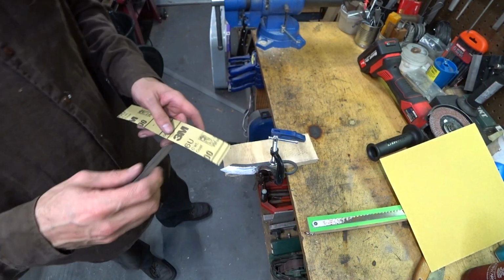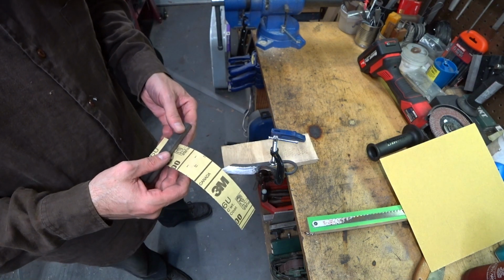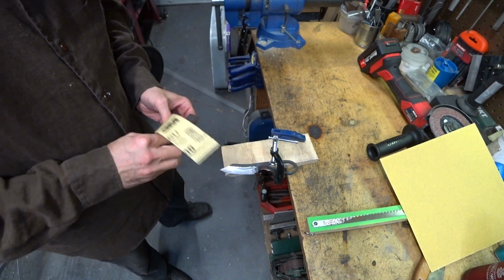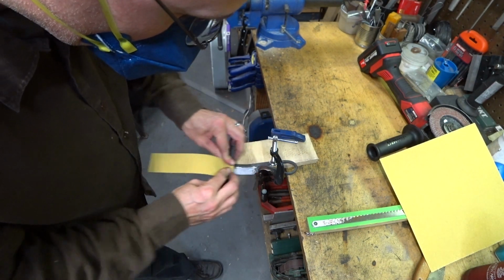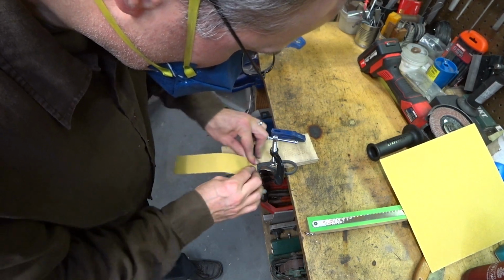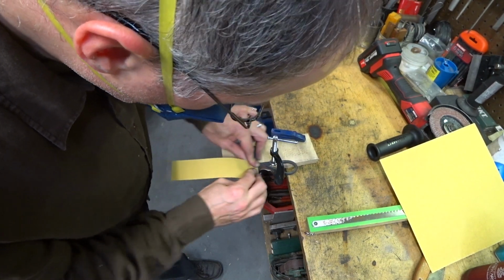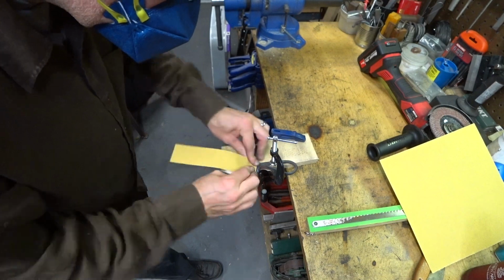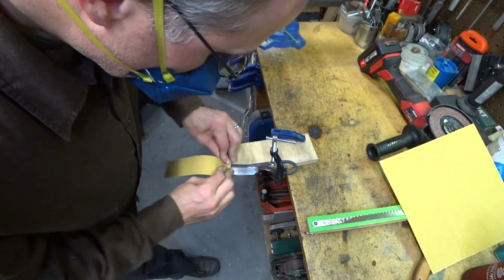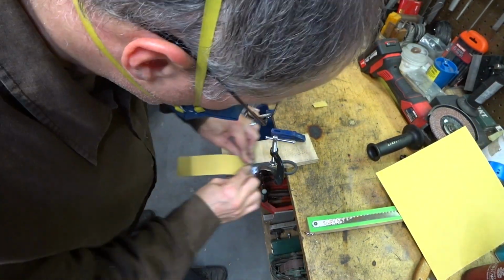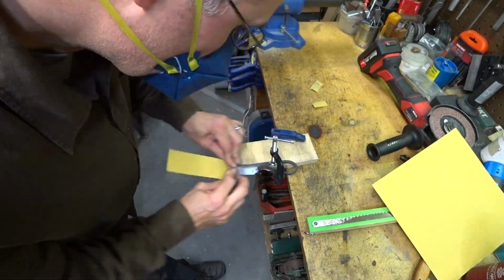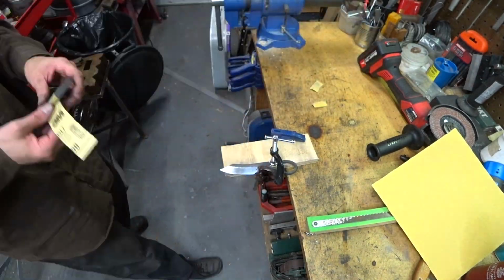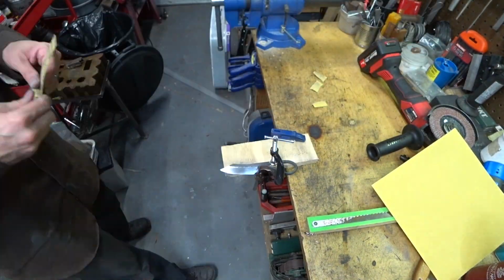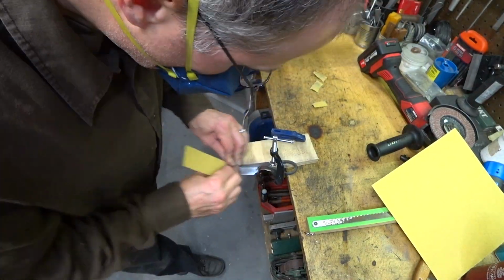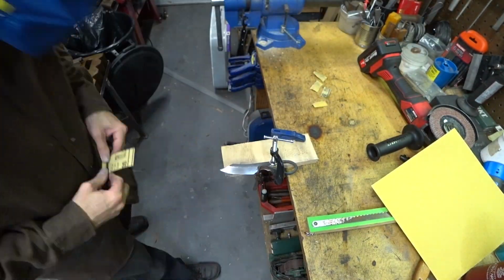I do think it's fairly important to get the largest scratches out of the blade before you do the heat treatment, because they can act as stress risers and increase the likelihood of cracking. And so I usually try to make sure that any scratches larger than about 80 grit I get rid of before I do a heat treatment. I'm really going to fast forward through this process as well, because watching hand sanding is almost as boring as doing it. It really is the biggest slog of any knife making project.